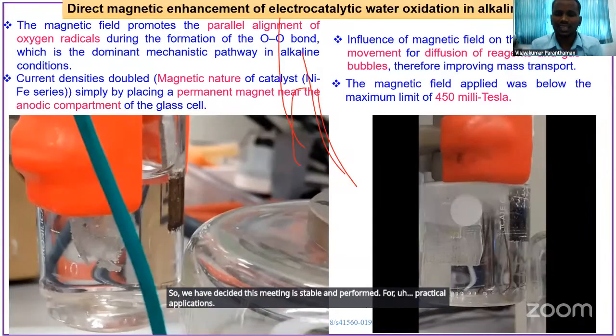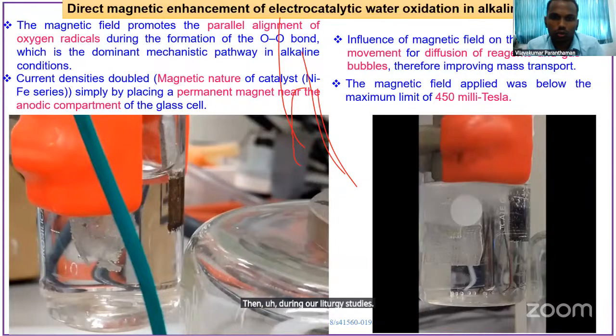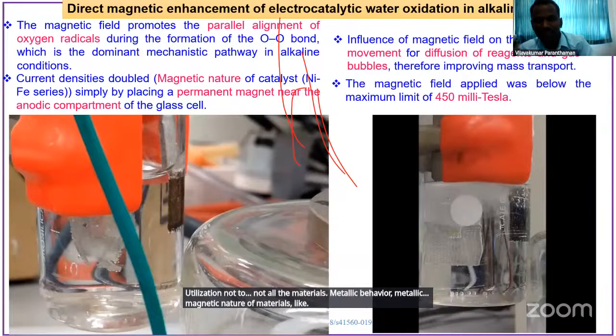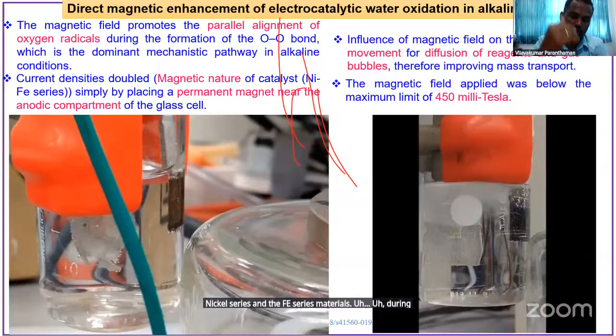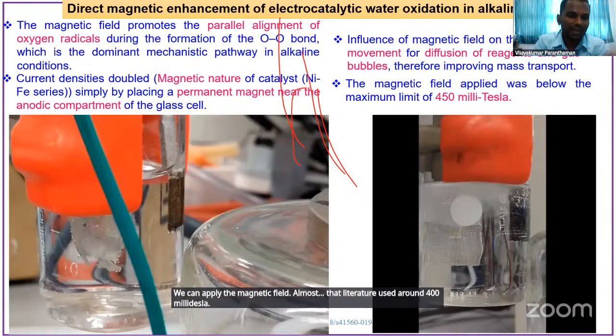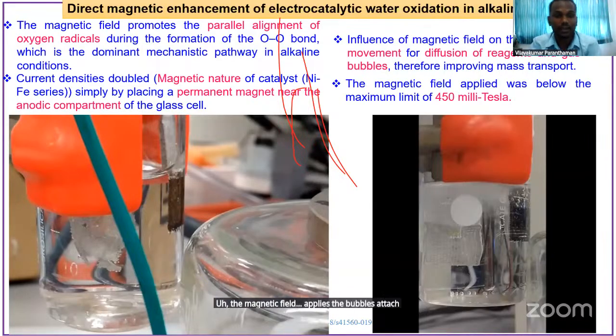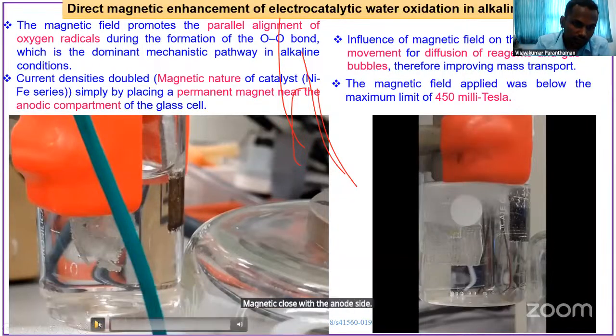Then during our literature studies, I went through one interesting study using a magnetic field to increase the water splitting potential. This magnetic field utilization works for materials with metallic magnetic nature, like nickel series and Fe series materials. During the OER activity, we can apply the magnetic field; the literature used around 400 millitesla. When the magnetic field is applied, the bubble detachment is getting higher. In-depth research is still ongoing. They mentioned that in a future paper they will discuss more about this. But we can clearly see more bubbles once the magnet is close to the anode side. Just see the video.